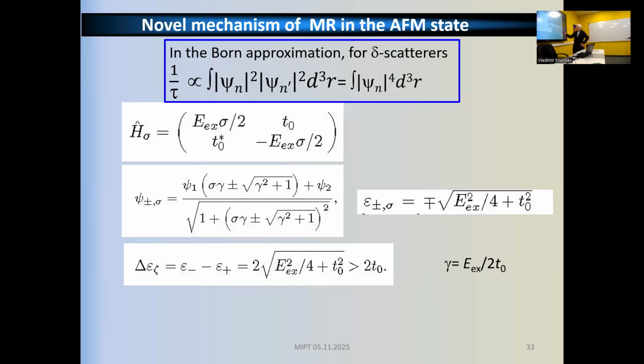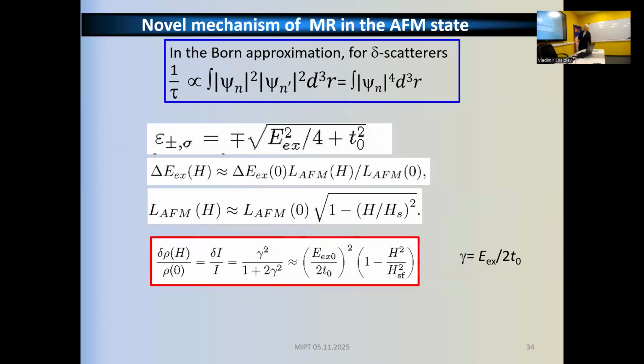MeV. Okay, so we have a certain dependence where T naught is a transfer integral across the layers, and this is the exchange splitting inside the layers. And the only parameter that from the theoretical point rules this effect is the ratio of the exchange splitting to transfer integral. A few more formulas. Where the magnetic field dependence comes from. It's not, of course, from T naught, which is a very large quantity, but exchange splitting does depend on magnetic field. When you fully polarize the system, it vanishes.